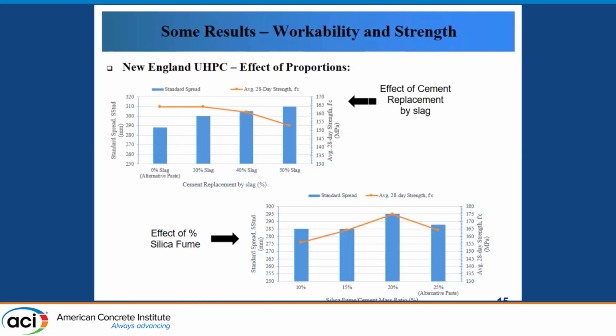Here, I would like to show some of the results. For example, you can see the effect of cement replacement by slag. We can see that all the mixes have exceeded the compressive strength of 150 megapascal while having sufficient workability, more than 270 millimeter every time.